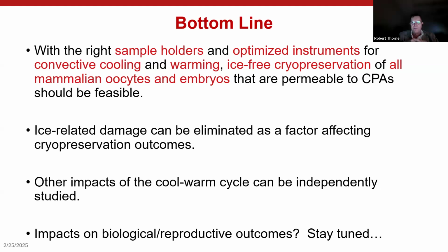Meaning if you drop a thermocouple down to the liquid nitrogen surface, it doesn't really start to drop until you get within 100 microns of the surface. That's probably not essential when you're talking about something that's 100 or 200 microns in size, but it was critical in cryo-electron microscopy vitrification of pure water. But it does matter, these things matter. I think the biggest thing is that not only is it fast using the instrument, but it's highly reproducible. And it's hard to get that reproducibility, even if you try to blow away the cold gas.